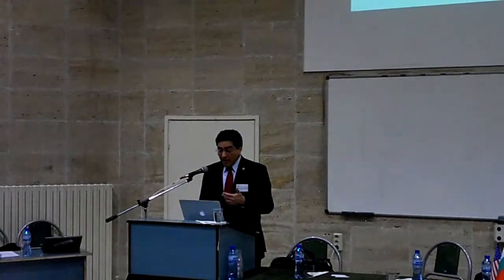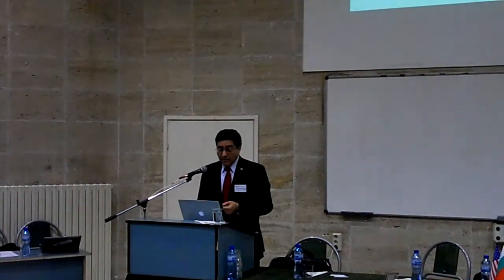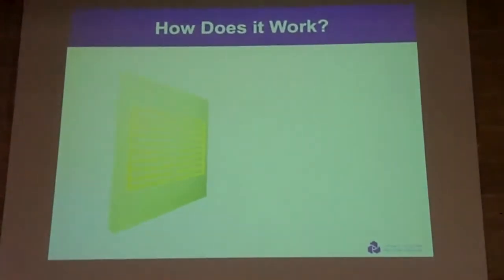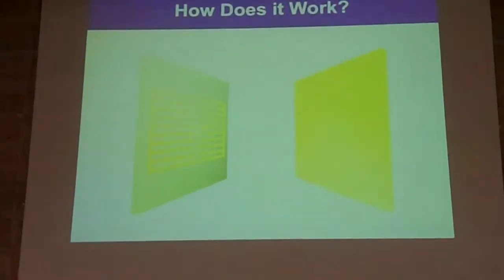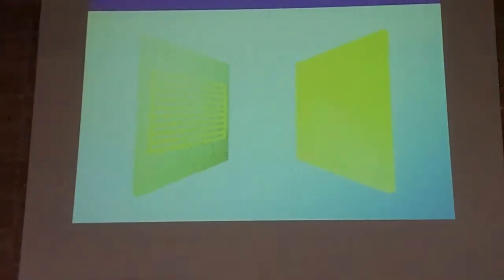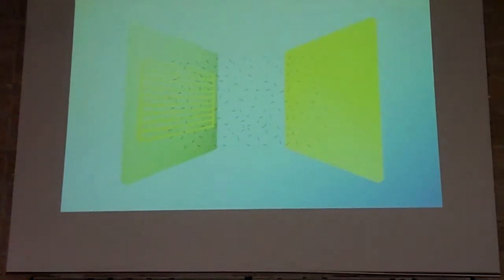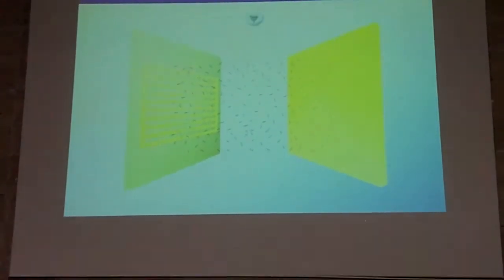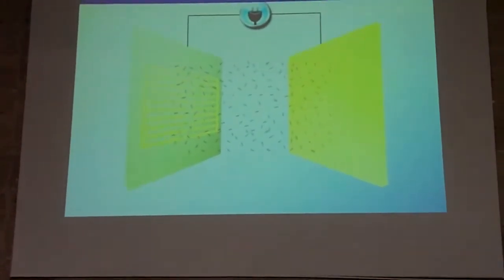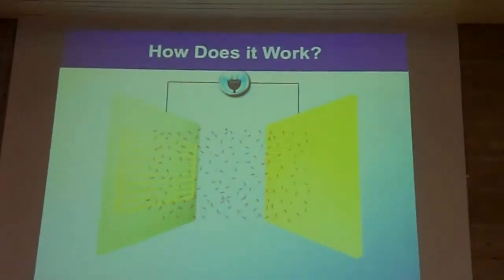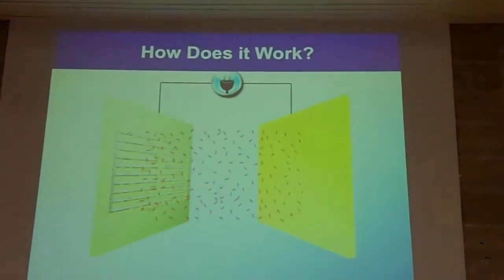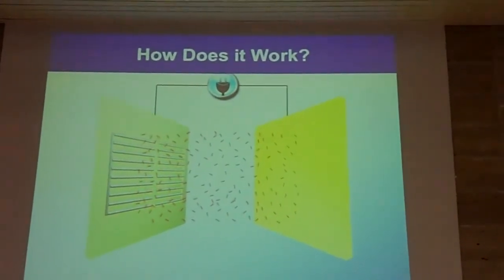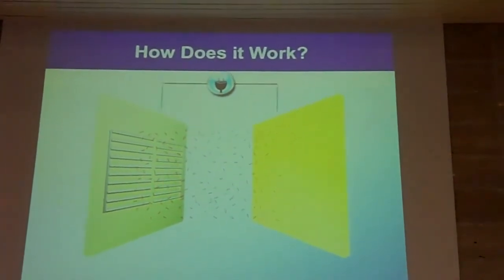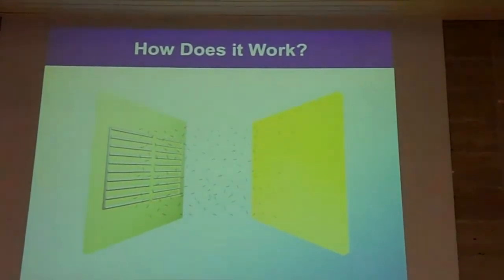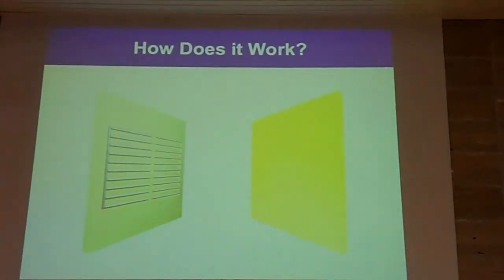So how does it work? Well, actually, it's very simple. This is a template that has a pattern. This pattern could contain your circuit or whatever you want to build. And then these are wires, which could be any conductor. You put them in solution, carbon nanotubes in this case, or nanoparticles, and you apply voltage between the two. This voltage, about 2 to 3 volts, that's it. And you attract all the nanoparticles, or nanotubes in this case, to the template, and you make the structure.